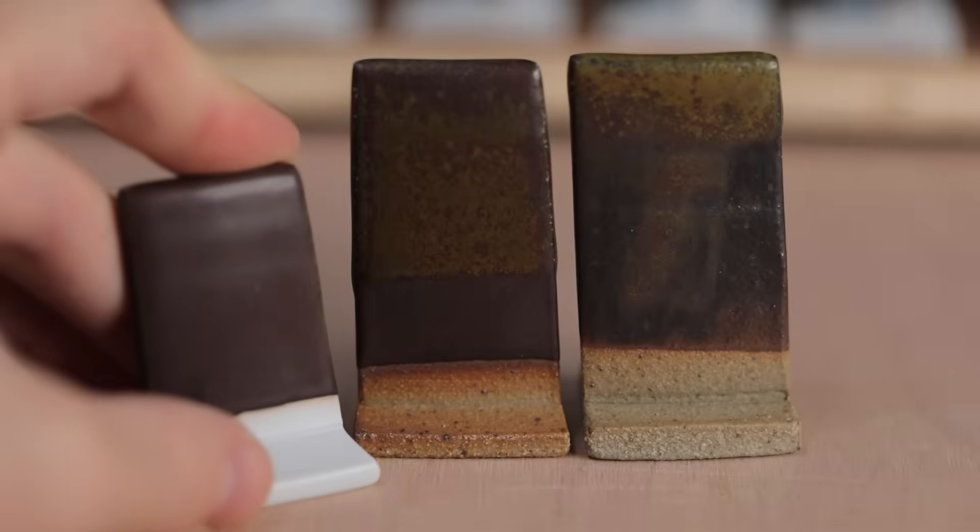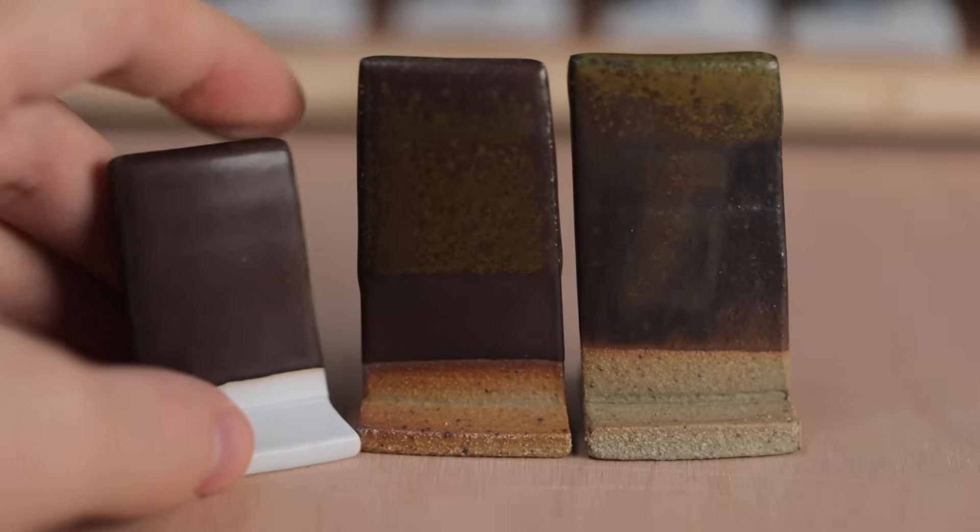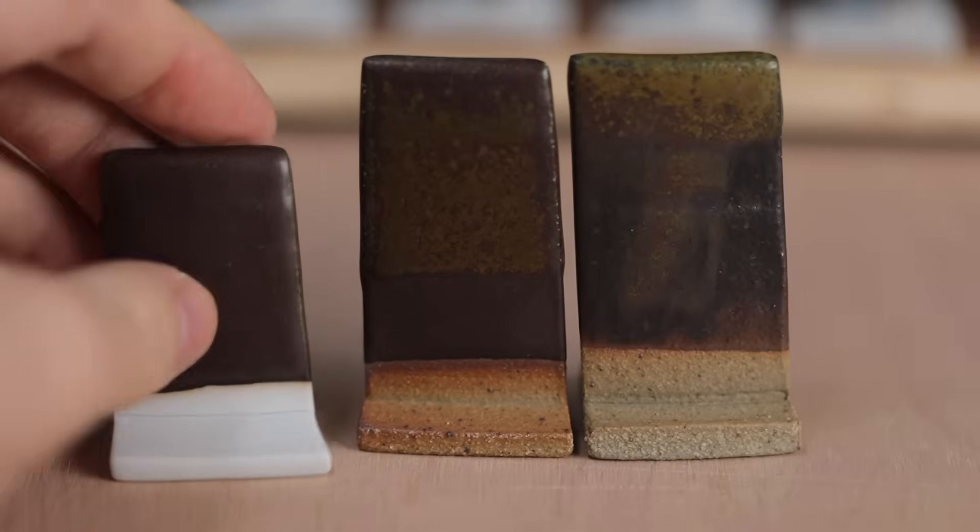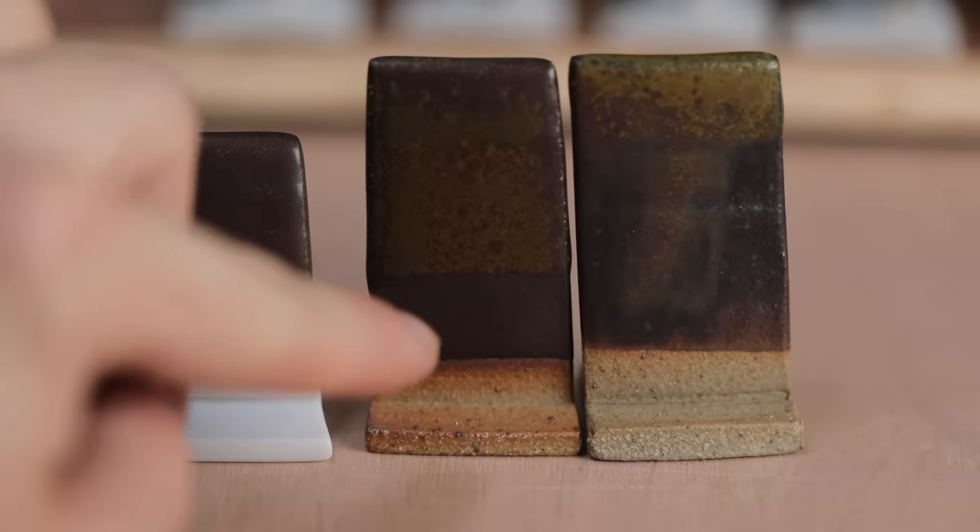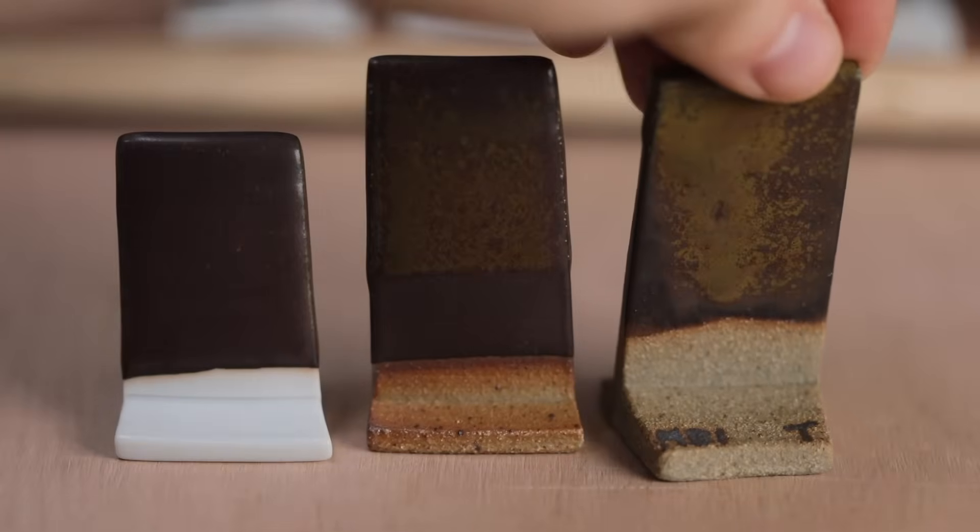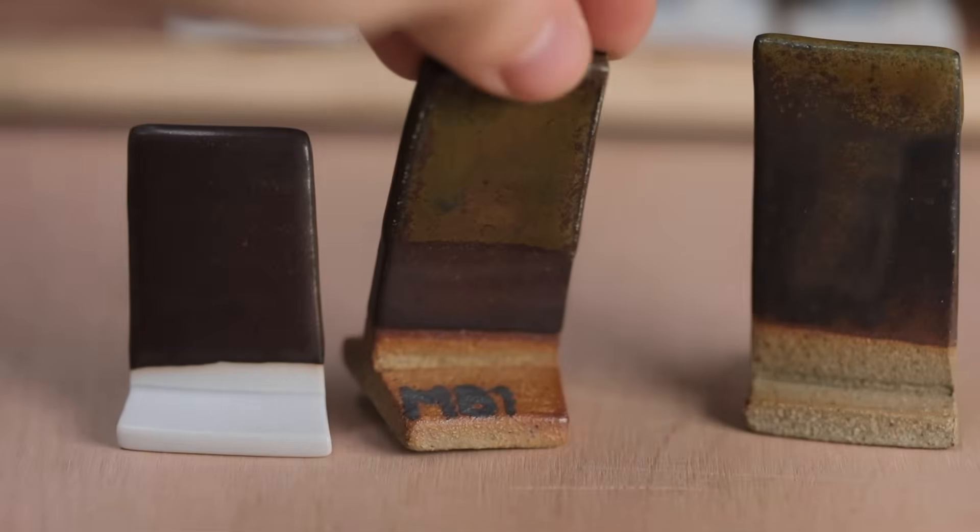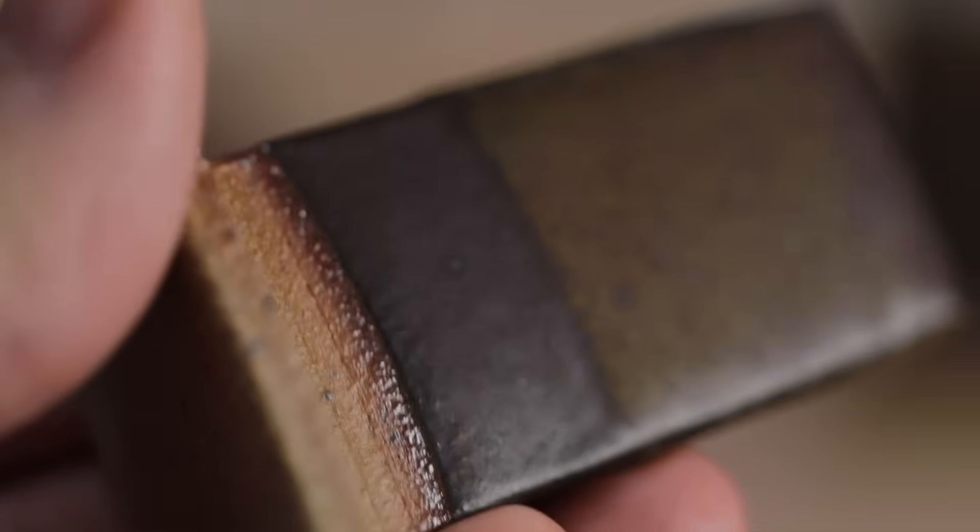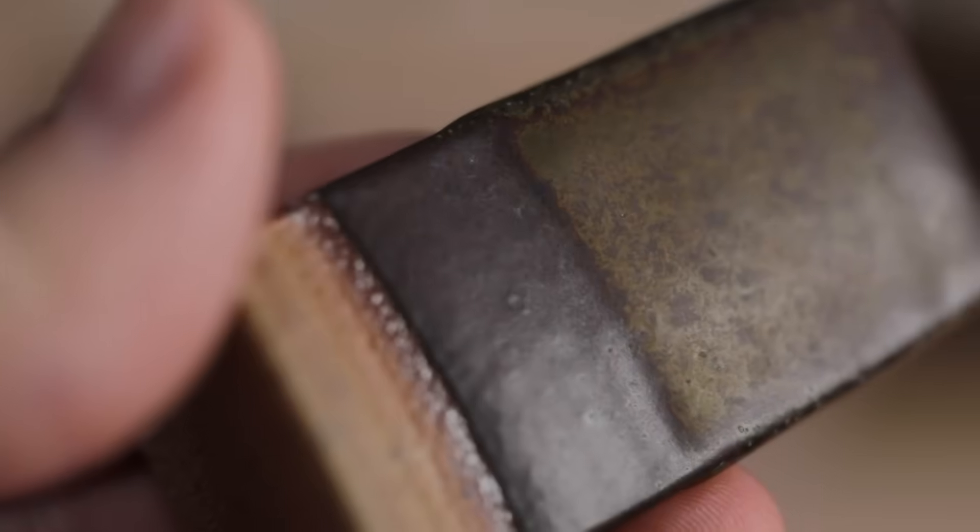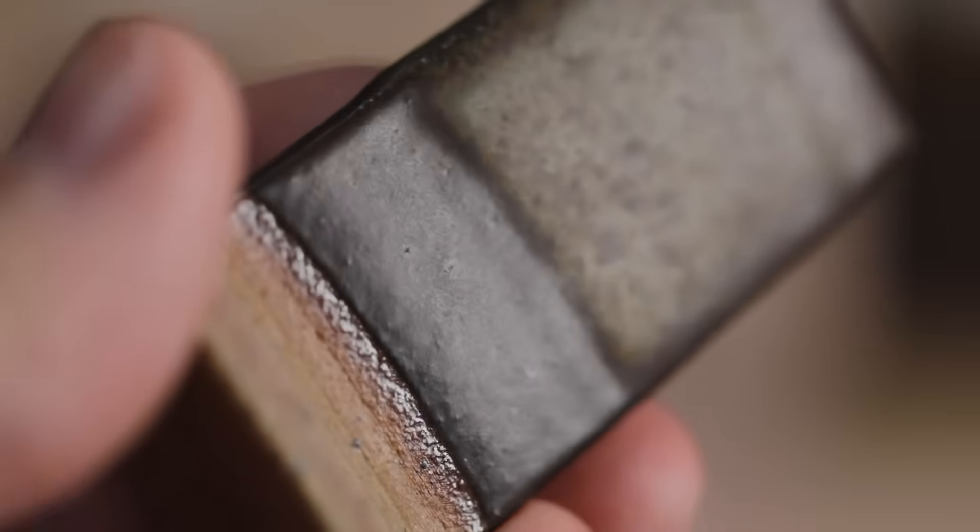Next are the glazes which I should hopefully start using. This one is a simple mix of feldspar, whiting, china clay, and flint, with a tiny amount of black iron oxide, and a minuscule amount of cobalt, and it feels like this one will be all about getting the application right, as the area I like the most is towards the bottom of this tile, where it's thinner, and where the green hues haven't started to appear. It feels like metal, and is wonderfully smooth, and on porcelain too, it's even nicer. It's also very stable, and barely runs whatsoever, which is very useful.